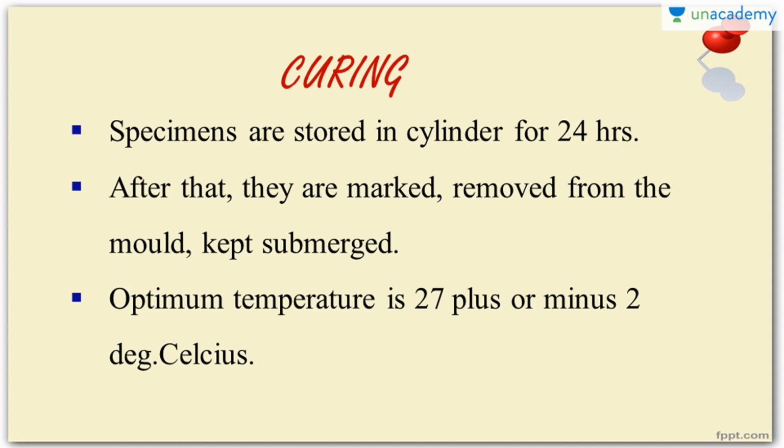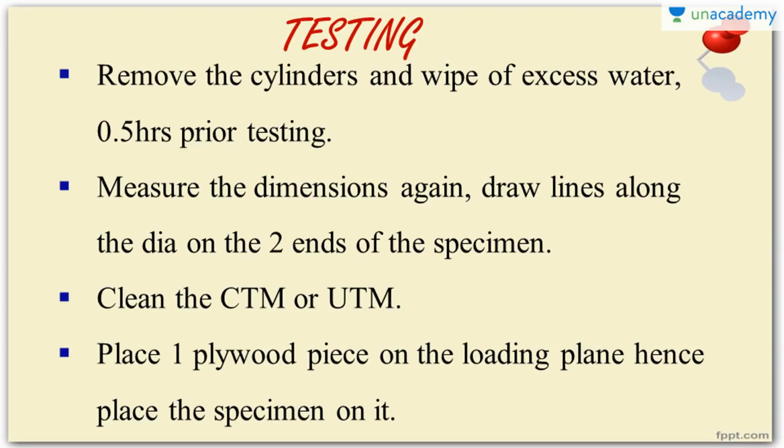It's a very simple procedure. Now, after curing, we need to go test the concrete. Half an hour prior to the testing, remove the specimen from the water. Wipe it nicely and allow it to dry to room temperature. Again, measure the dimensions of the specimen one more time. Now, draw lines along the diameter on the two ends of the specimen. This is to make sure that the specimen is kept properly in the CTM.